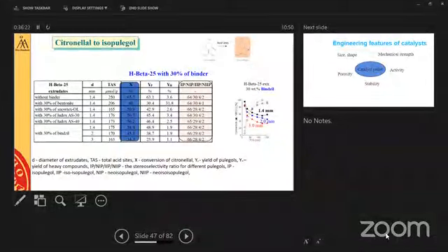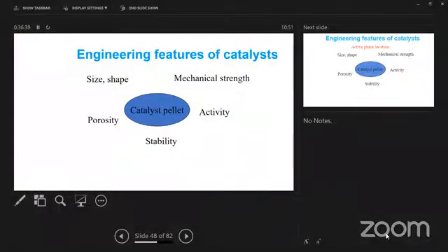Selectivity is the key. If you go to oil refining, it might be 0.1%, and that brings you a huge amount of revenue. But here, at least that's good news for scaling up of this process, that selectivity or the ratio between the isomers didn't change that much.